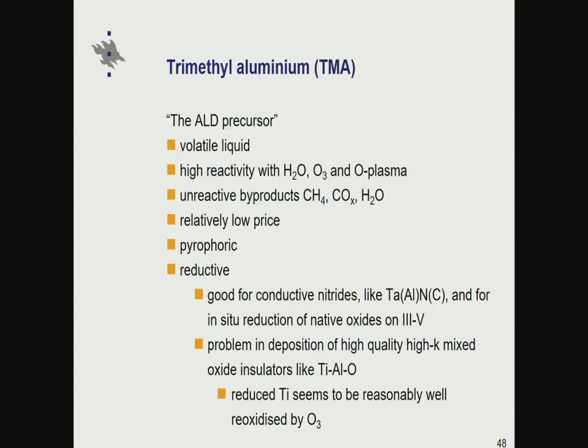Trimethyl aluminum, well, it was mentioned already, but it is really the ALD precursor. If all precursors were like TMA, we would be in a much better position taking ALD to new application areas. But they are not. But this is really something, it's setting the requirement or the goal, what we would like to have from ALD precursors.